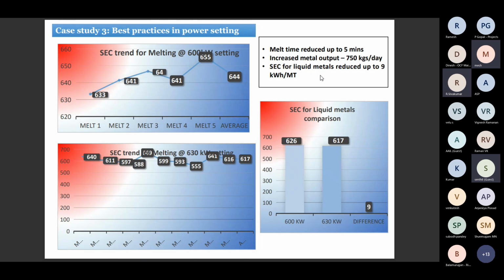750 kgs extra melt can be taken, and the specific energy consumption of the liquid metal is also reduced by up to 9 to 10 kilowatt hours per metric ton. This 644 and 617 is for the complete melt sequence. Here the SEC is also reduced by up to 9 kilowatt hours per ton. Next.